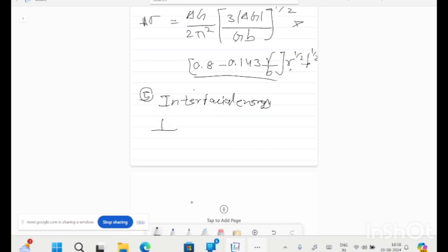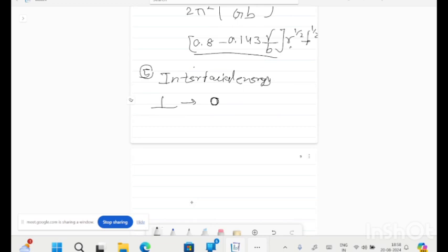If a dislocation comes in front of a precipitate, it will cut through the precipitate if the precipitate particle is smaller than a certain size, and a sheared particle will form.